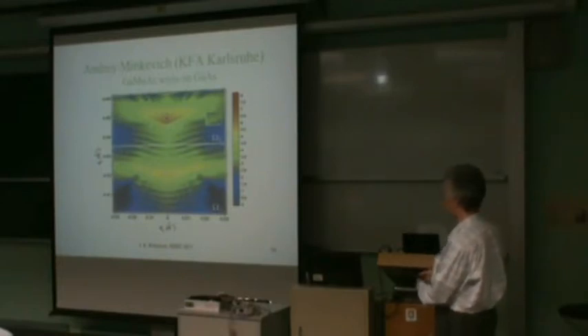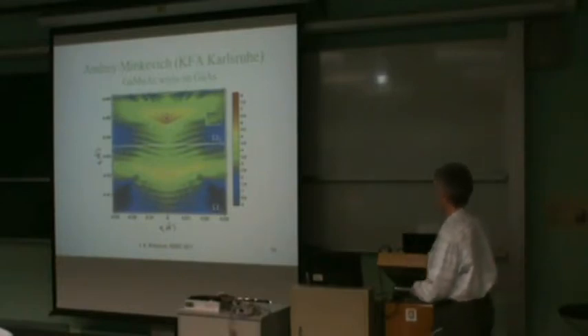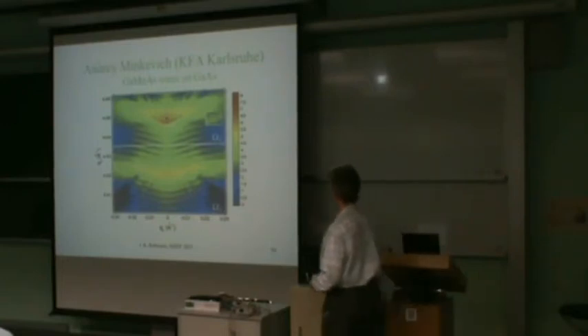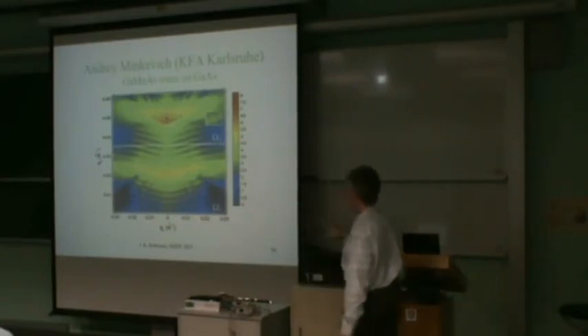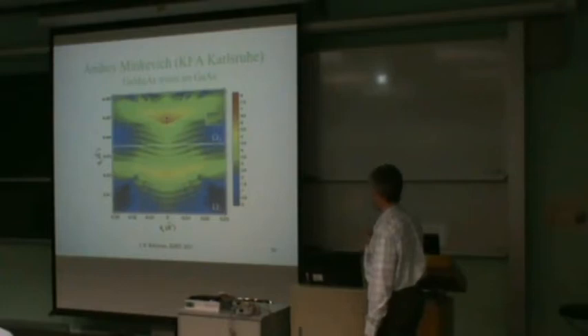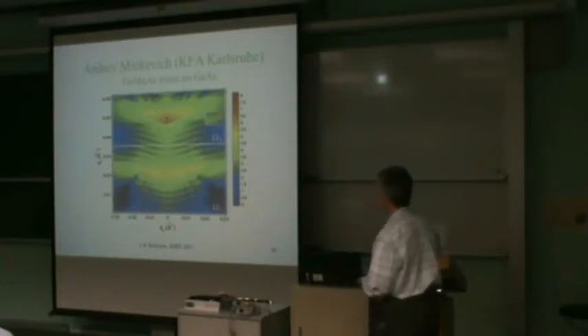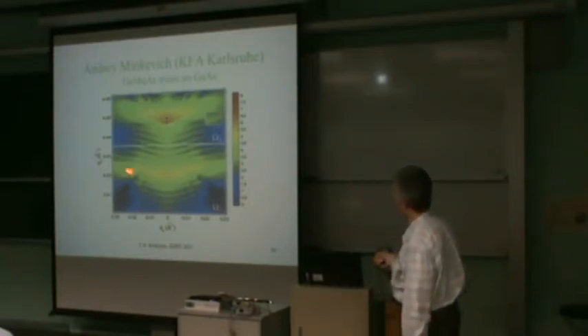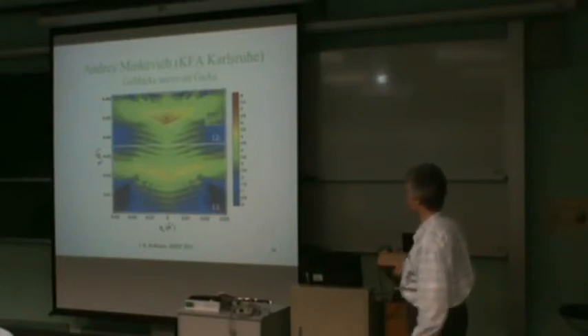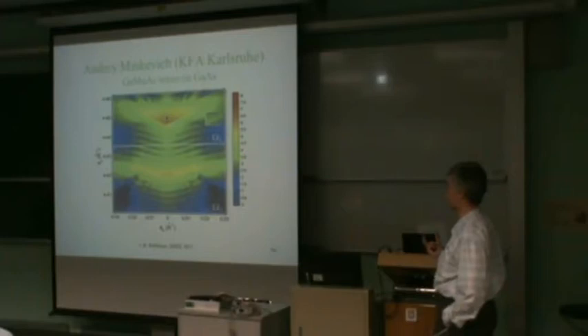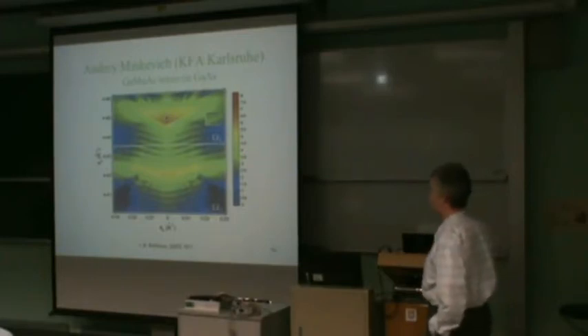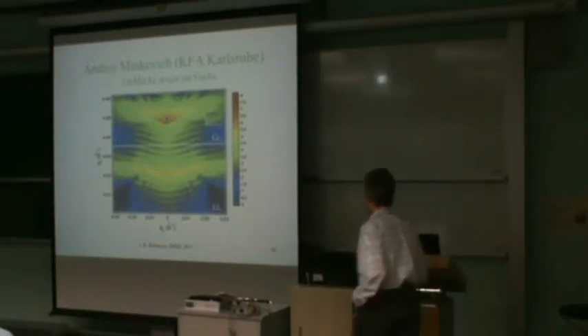And you can see you get this very rich distribution of intensity, lots and lots of fringes. And this is an example where, instead of getting a single center of the bright peak, you have a distinctly spread out center. And this is the case when you have the strain bigger than 2 pi, and you have actually to do some work to be able to get this to invert.